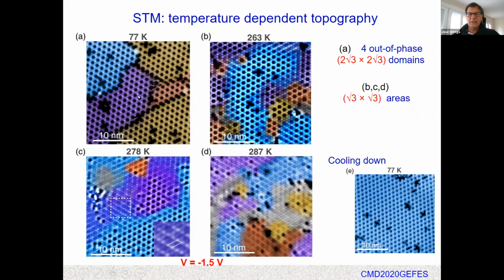Now, when you increase the temperature and you get close to room temperature, we start to see in these STM images also a √3×√3 lattice, which is shown in these gray areas. These gray areas that you can see in the images have a √3×√3 lattice for the tin atoms. And then if you cool down, you now produce a single domain at 77 Kelvin.